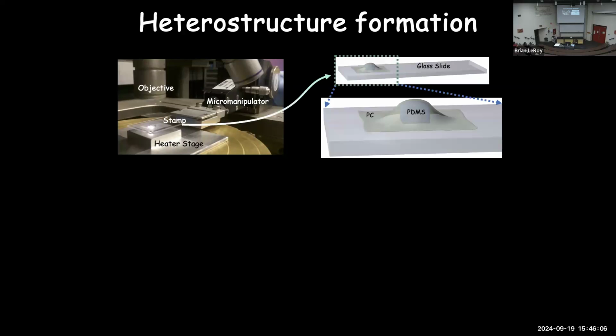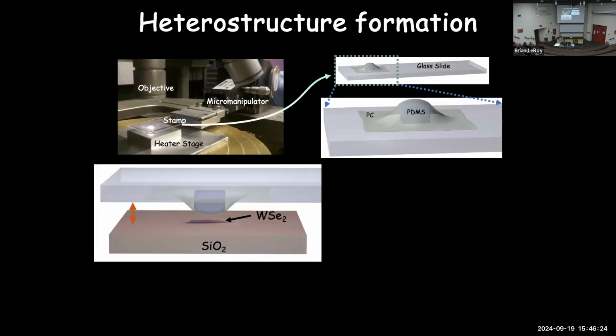And so in a more close-up view of what this looks like, we have this polycarbonate plastic structure on a PDMS stamp, a little squishy plastic here. We take this little bump, flip it over, and bring it into contact with our sample, like that. As we come into contact, we heat up the substrate. That expands the polymer a little bit. It then becomes sticky. As it cools, it will pick up the material that's underneath it and bring it up onto the stamp. So down, heats up, and we've picked up the material onto the stamp.